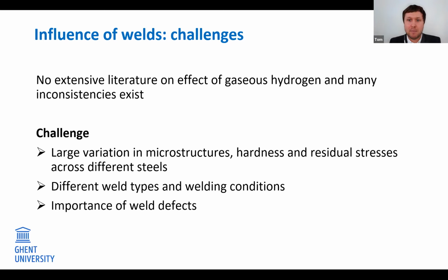Welds in pipelines are typically the region in which most defects can be found. And we know already that defects can interact with hydrogen because they can trap hydrogen, they can affect diffusivity. So these are critical regions, and they can be more sensitive to fatigue crack initiation. However, there is no extensive literature yet on gaseous hydrogen, and many inconsistencies exist in the literature.